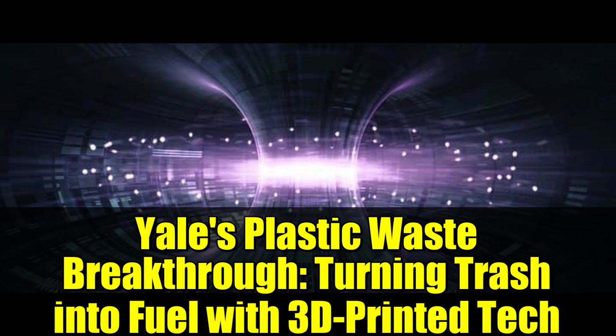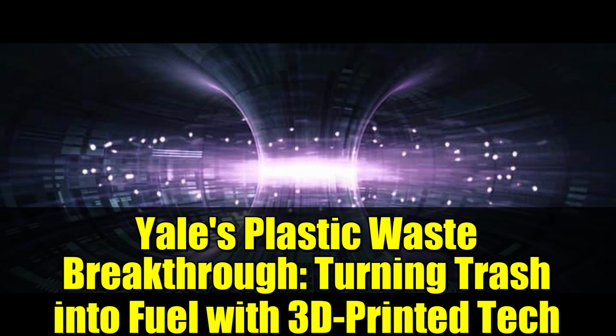A group of Yale scientists have engineered a novel device that can efficiently transform plastics into fuel without relying on any catalysts. Even more impressively, their innovation extracts 66% of fuel-relevant chemicals from polyethylene, surpassing previous technologies. So what's their secret? The team designed a 3D-printed, electrically heated carbon column reactor composed of 3 sections, each with progressively smaller pores. These varying pore sizes help carefully manage the chemical reactions, which is a significant leap in optimization.